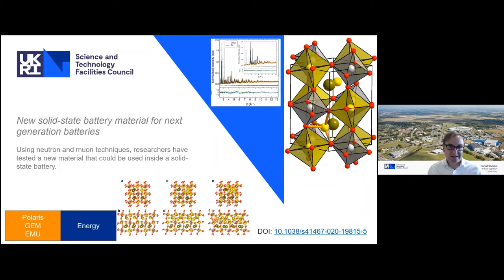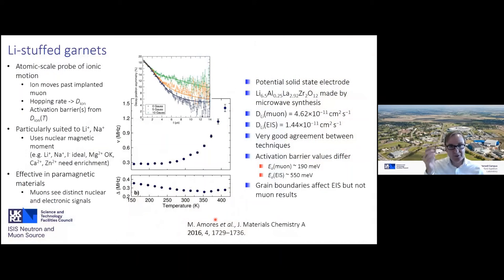Of course, you might also like to know how those lithiums are moving around in the system. This is where the muon technique can play an important role. Recall that muons are sensitive to the local environment. If a muon implants itself into a structure at a place where there's a large electronegativity, then as the lithium ion, which has a nuclear moment, moves past the muon site, it perturbs the local magnetic environment, which the muon senses.